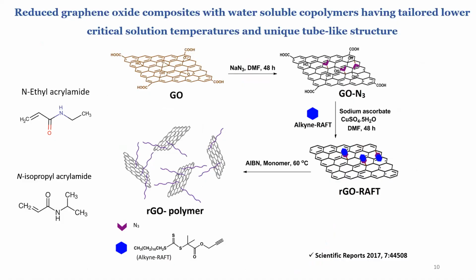We started with N-ethyl acrylamide and N-isopropyl acrylamide monomers. The structures of these are shown on the left side. As you can see, N-ethyl acrylamide has one less methyl group, which makes it a bit more hydrophilic than the other monomer. The graphene sheets were modified by azide, and I designed an alkyne RAFT agent. This RAFT agent was suitable for the polymerization of these two monomers. And then they were clicked together. During the click reaction, graphene sheets were also reduced. Then we prepared homo and copolymers using these two monomers.